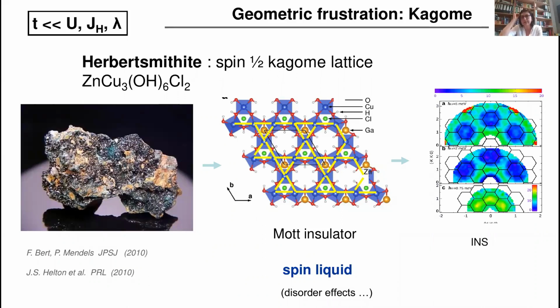If we think about geometric frustration, one of the most studied materials is a Mott insulator called Herbertsmithite, which is a mineral. It's built of layers of copper atoms, which have a localized spin 1/2 on a kagome lattice. For a long time, this system has been proposed to have a spin liquid ground state.